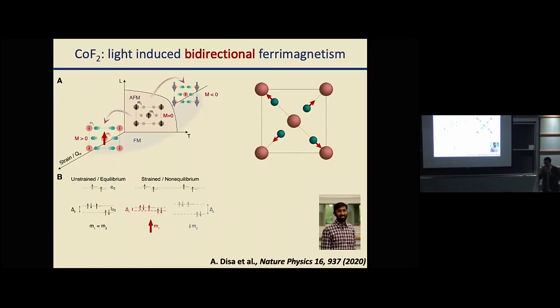So unlike magnetostriction, this couples strain and magnetism at linear order, so it allows me to have positive or negative ferrimagnetism. And so he basically applied three-phonon mixing to drive the equivalent of piezo-magnetism using optical phonons alone, so at constant volume. And he could show that you could generate magnetic order, ferrimagnetic order in either direction, at amplitudes at least 1,000 times larger than what you can do with piezo-magnetism, because volume-preserving excitations don't crack the crystal. And so he could basically emulate what strain does, but push it much further, and do it faster, etc.